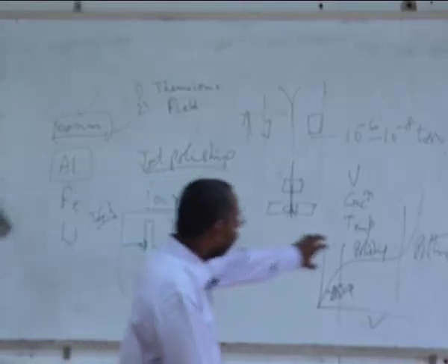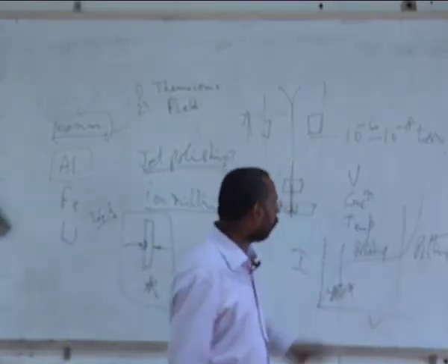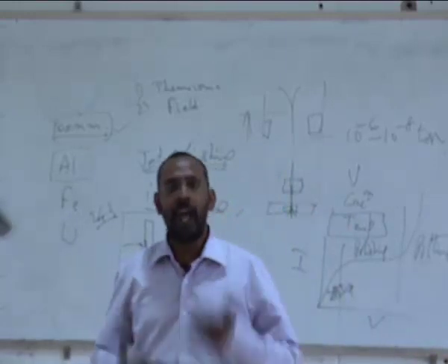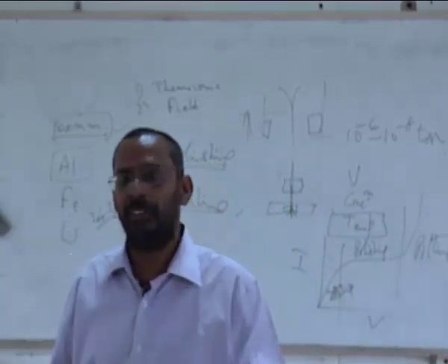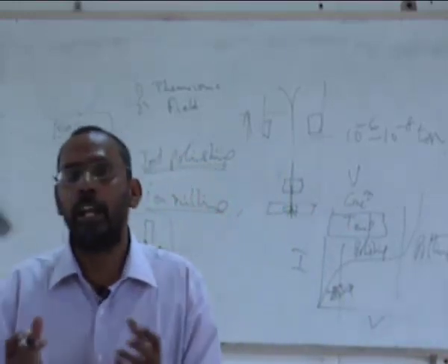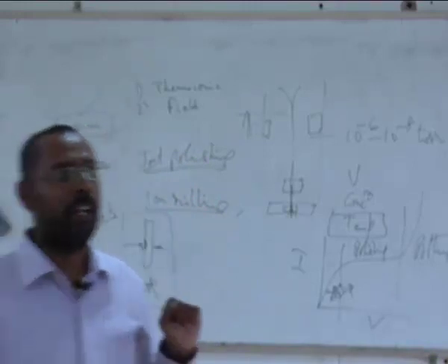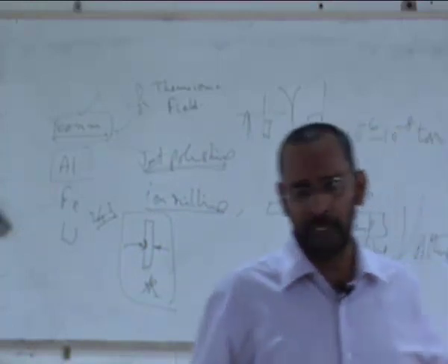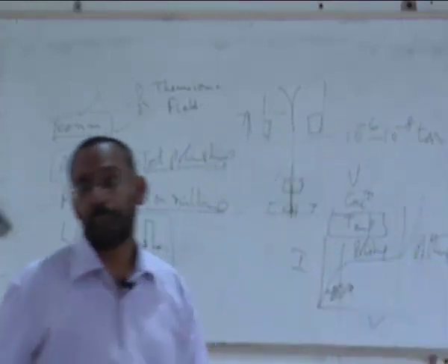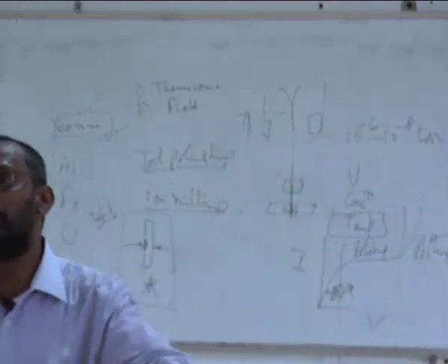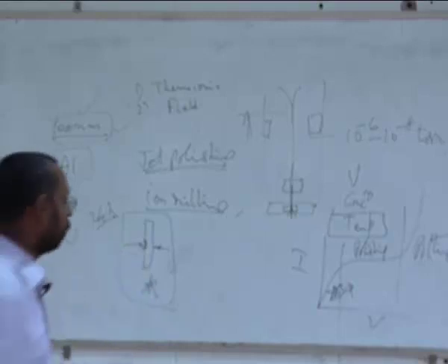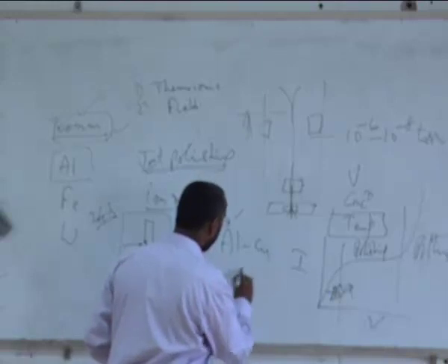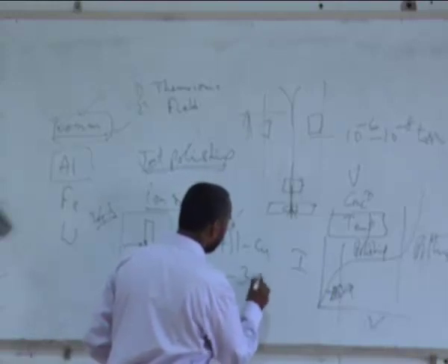So this domain has to be identified. And also, if the temperature is higher, then the material has a tendency to dissolve very fast. As a result, you are not able to catch that particular instant where just a hole has formed. So as a result, many times we do this jet polishing at temperatures which are below 0 degrees. In most cases, for example, if I am making an aluminum copper alloy, generally we use about minus 30 degrees centigrade.